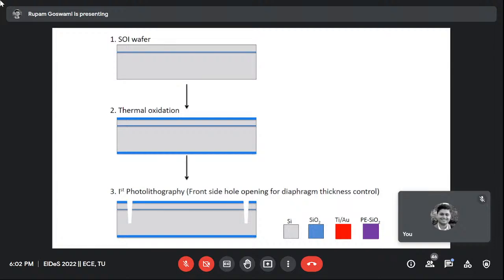So this is the stage where, if you go back and recall, with polysilicon we deposit it and then we dope it. Here doping is also already available because the required resistivity of the active layer is there. And the quality and the thickness of the oxide is also there. Only we have to do the lithography and the patterning for the resistors. So in this slide, some more extra processes are also there, thermal oxidation. But thermal oxidation is not required if you have the right kind of SOI wafer with the oxide thickness, the active layer thickness and the resistivity. Then you don't need these steps which have been shown over here.